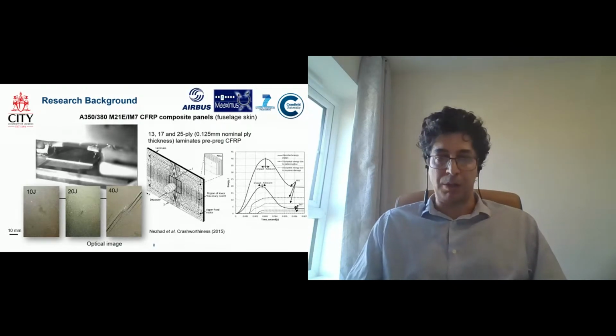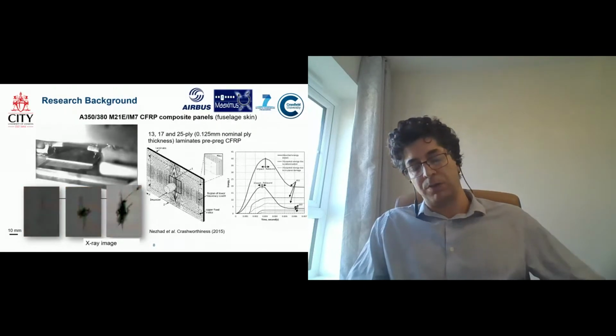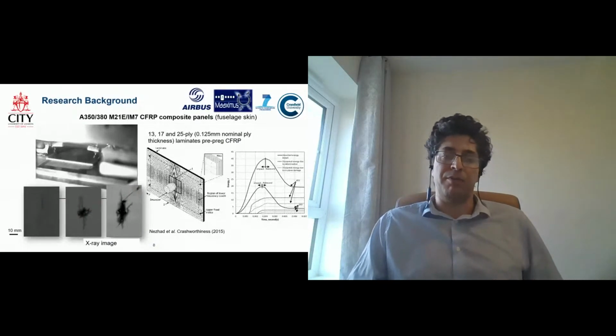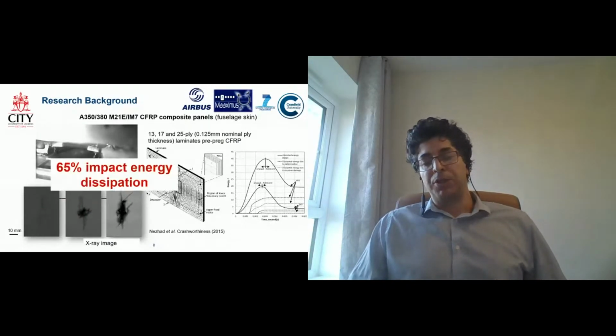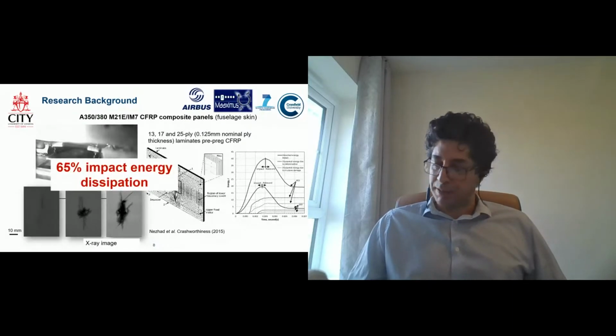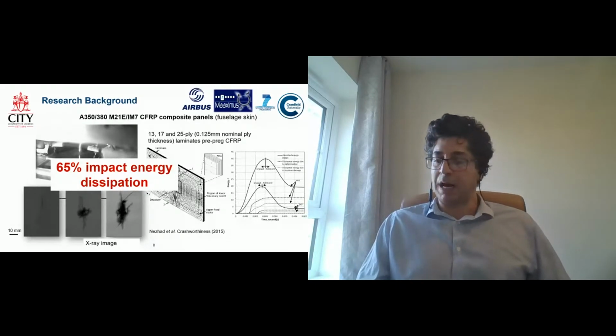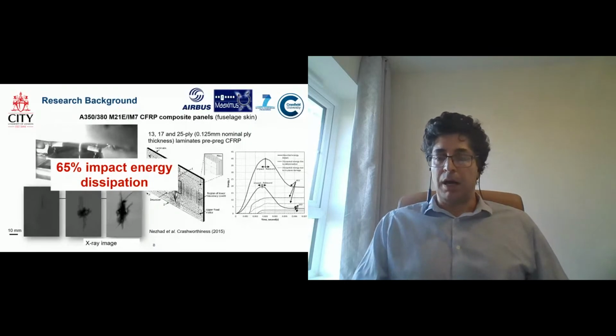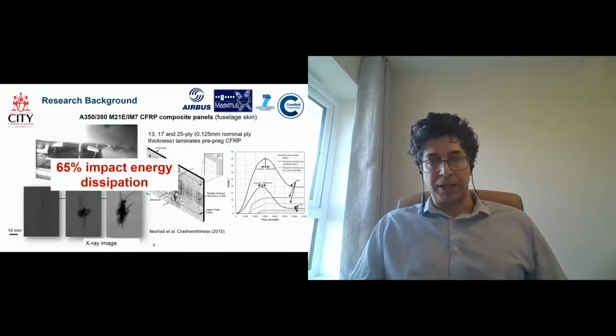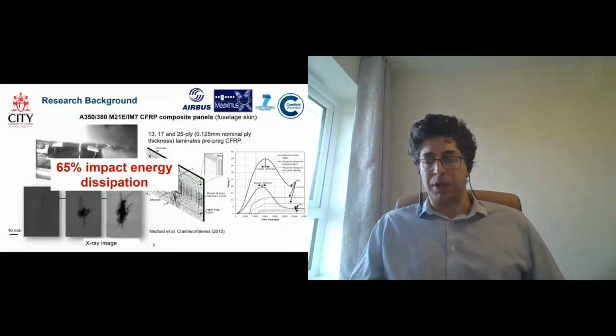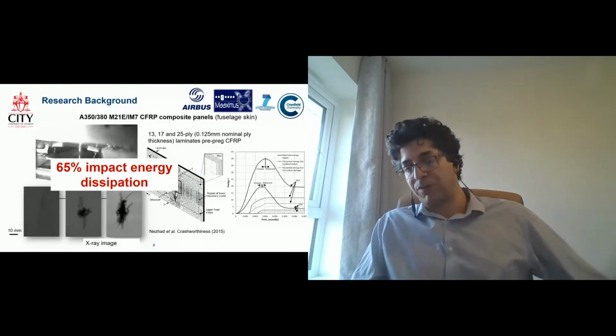I mean, that material, M21, has been used in the A350 already. But if you scan it or do the X-ray measurement, you see there's substantial damage inside, which needs to be taken care of. And bear in mind that a majority of this impact energy is dissipated by a very devastating sort of damage called interlaminar delamination, based on our research, of course. And there are loads of improvements towards moving to thermoplastic layup using automatic placement. It doesn't eliminate the danger of ending up with interlaminar delamination, which is quite dangerous because, first of all, it's very difficult to see.